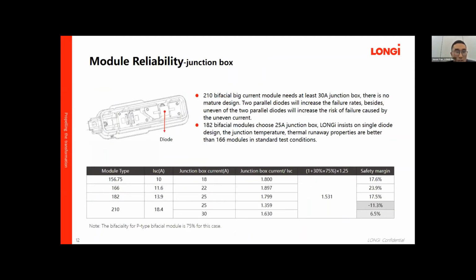And also for the junction box, when we look at the history trend of the junction box, we can see we always use a junction box current higher than the theoretical current, from the 156.75 module to the 182. So the safety margin is over 10%. And for the 210 bifacial module, if we use the 25 amps junction box, that is not enough, so we need to use at least a 30 amps junction box. Normally, 2 parallel diodes are used in the 30 amps junction box, and that will increase the failure rate. Besides, the unevenness of the 2 parallel diodes will increase the risk of failure caused by uneven current.